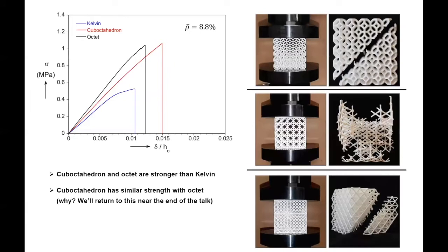Can I interrupt you? So you apply sigma. So you are interpreting this as material response. What happens when you make these specimens larger and larger? Right, we did that. So they look small here, and they are, but we did 5 and 6 and 7 to make sure that we always get the same answer. You always get the same. It asymptotes. Yeah. And typically the rule of thumb is go 10 by 10 by 10.